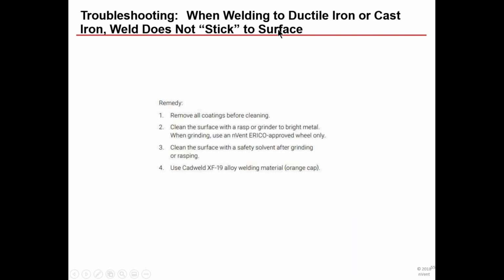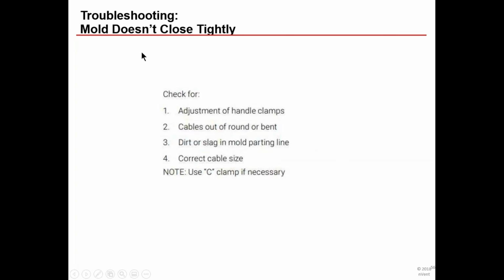So here's a few things. When welding to ductile iron or cast iron, if the weld does not stick to the surface, again, make sure the coatings are removed, hit it with a rasp or a grinder, make sure the metal is bright, and clean the surface. There is also a product you can use called Cadweld XF19 alloy welding material, which is a little bit different, but will allow you to do that. If the mold does not close tightly, you need to see if your clamp needs to be adjusted.